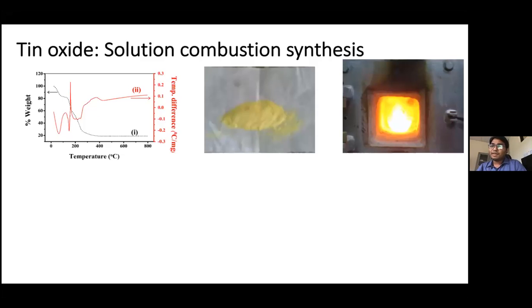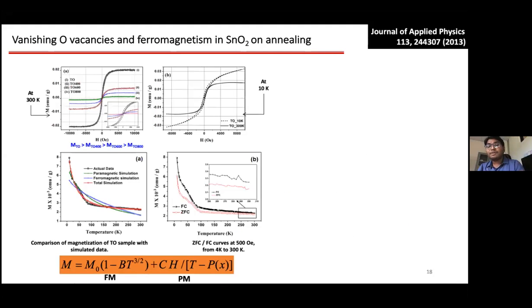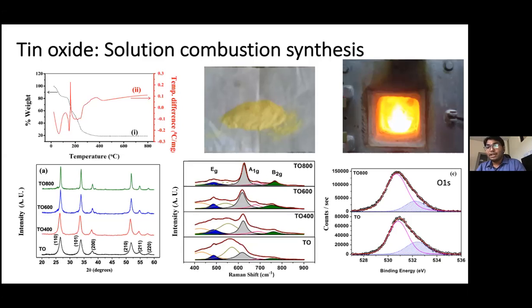We did it on that vibrating sample magnetometer. And to my surprise, I got a somewhat noisy ferromagnetic loop. I was surprised that either I had got some kind of impurity, or this machine had gone bad. These were the only two possibilities I could conclude at that time. And what I found was that it was indeed showing it. Then we made some more magnetic measurements on a more precise system, which is a SQUID magnetometer, which can detect very low magnetic moments in the sample. That confirmed that it indeed had some kind of magnetic moment, and it was showing a saturating magnetic moment with the field.